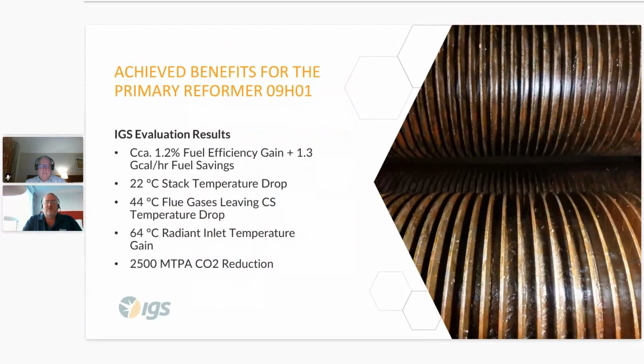So the whole thing was about returning fuel efficiency. So we managed to get a fuel efficiency recovery in the region of 1.2%, which gave them an efficiency gain of 1.3 gigacalories per hour on the fuel. A 22-degree stack temperature drop is always a good indicator for us guys, because when we like to see that distinct stack temperature drop, us simple people, if we see a simple stack temperature drop, then we know that you're saving a lot of fuel.